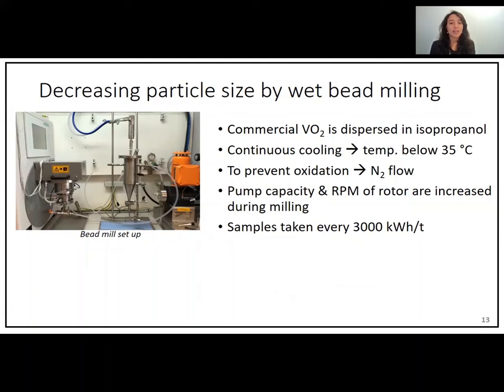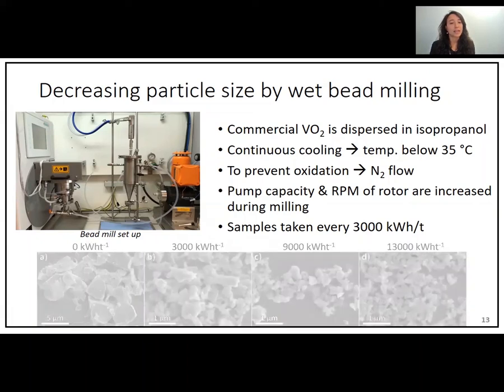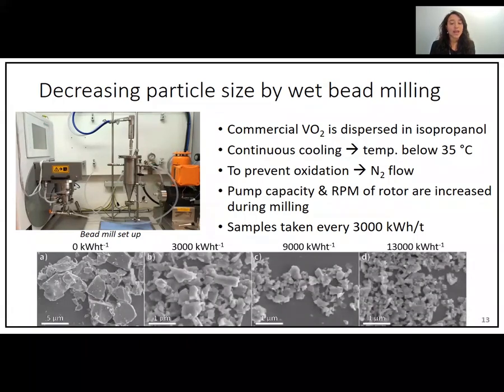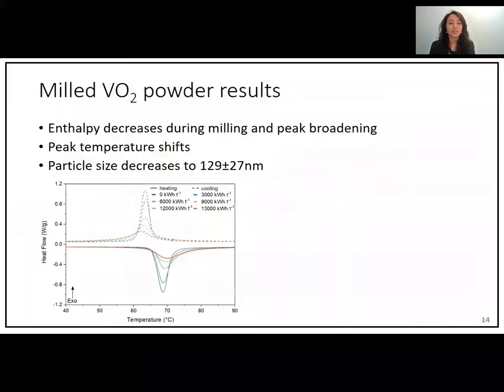But there are many different parameters which can be changed during the milling, and mainly the pump capacity and the rotation of the rotor are increased during milling. If we look at the SEM images of different samples taken every 3,000 kilowatt hours per ton, we can see that the particle size decreases from about 5 microns to nanoparticle size between 100 and 150 nanometers.